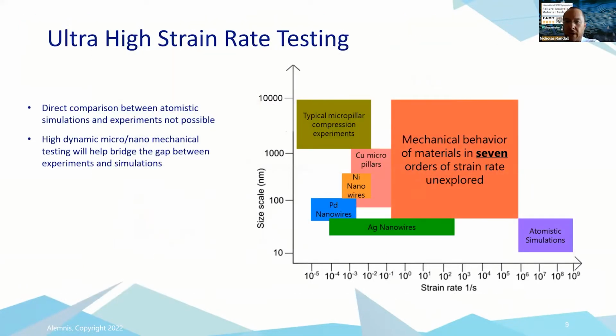So a quick overview of different speed testing, because this is quite unique. When we test at different speeds, we can look at the strain rate sensitivity of materials. At the moment, typically nanoindenters are testing in very slow regime speeds, typically 10^-1, 10^-2 down here. And what's interesting is this red box, getting up to strain rates of 10^4, 10^5, which are very fast.